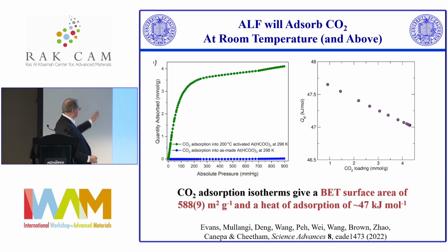And from the isotherms as a function of temperature, we can get the heat of adsorption, which is about 47 kilojoules per mole, depending on the loading. And we also have the BET surface area and isotherm from the same measurement. So that's nearly 600 meters squared per gram.